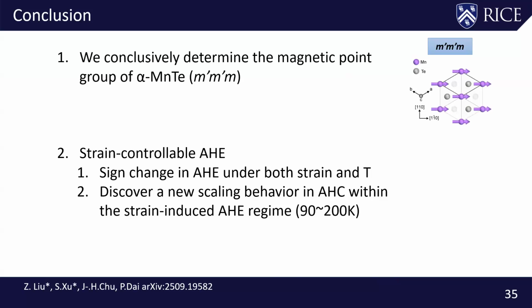So what have we learned? We have learned that in the case of pure manganese tellurium, the anomalous Hall effect can only be seen when the charge gap of the system is roughly around 18 millivolt. That basically means that the fact that the system is a semiconductor is exceedingly important in terms of where you can see anomalous Hall. And the second thing we have learned is that the anomalous Hall effect in such a system is really associated with altermagnetism, because we have shown conclusively the magnetic structure of the system is M prime M prime M, which can give rise to anomalous Hall effect due to Berry curvature. And that's the second conclusion we have reached.